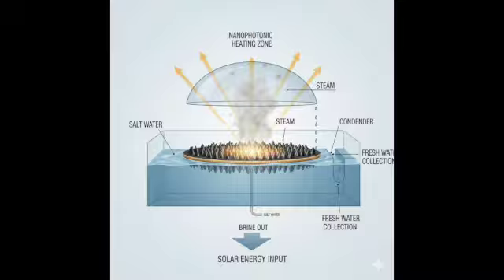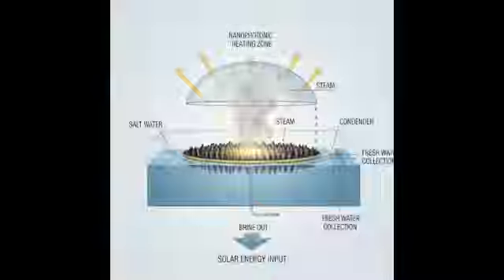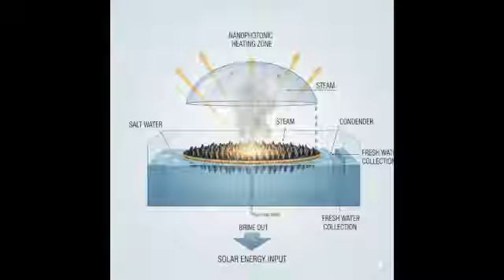Generally, yes. Metals, on the other hand, are all about the heat. How do they work? Plasmonic resonance. Exactly. Nanoparticles of certain metals, especially noble metals like gold and silver, but also others like aluminum, exhibit surface plasmon resonance. When light hits them, it excites collective oscillations of their surface electrons. Then that generates heat. This resonant absorption is very efficient at converting light energy into localized heat, essentially Joule heating